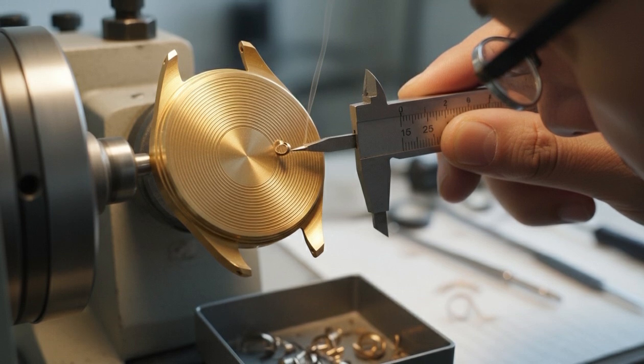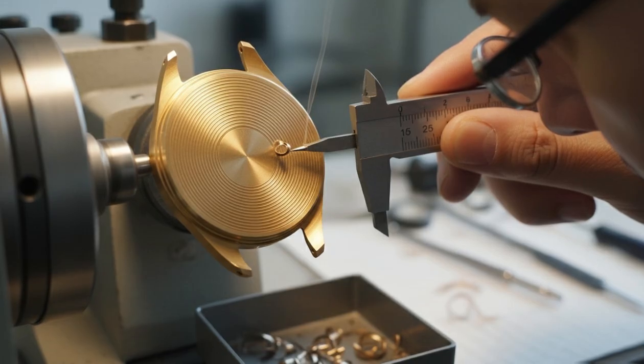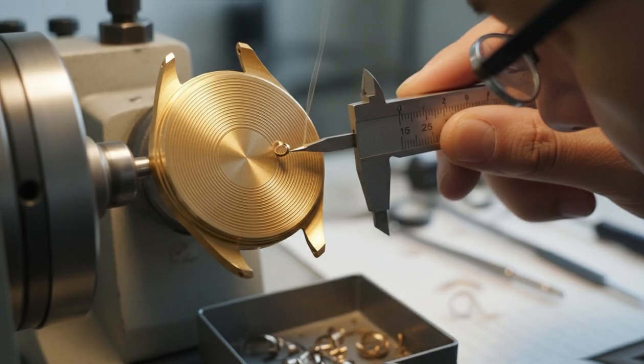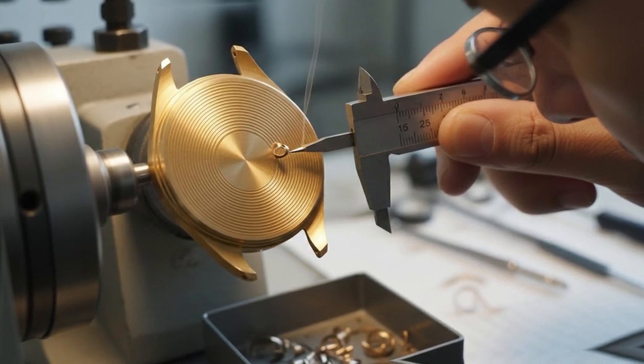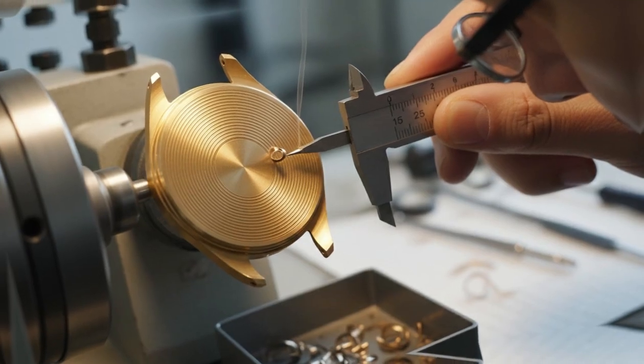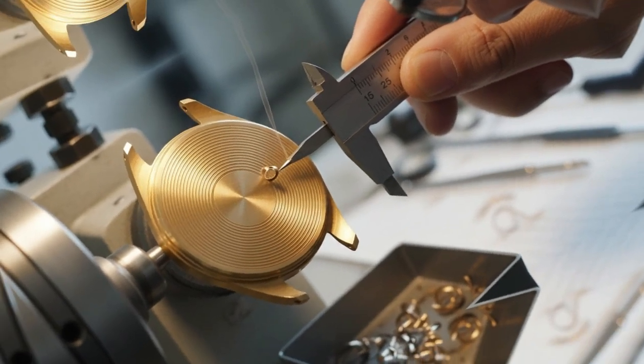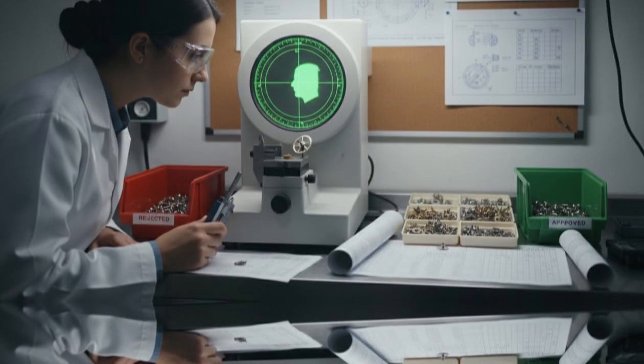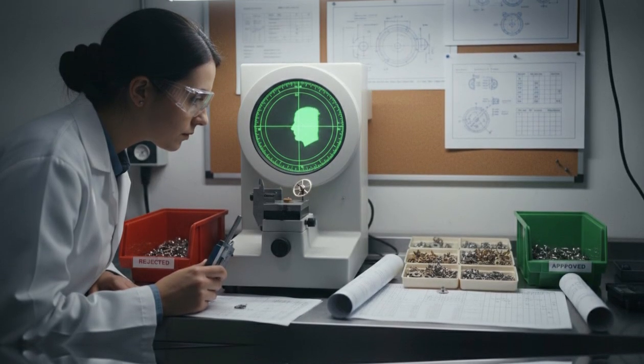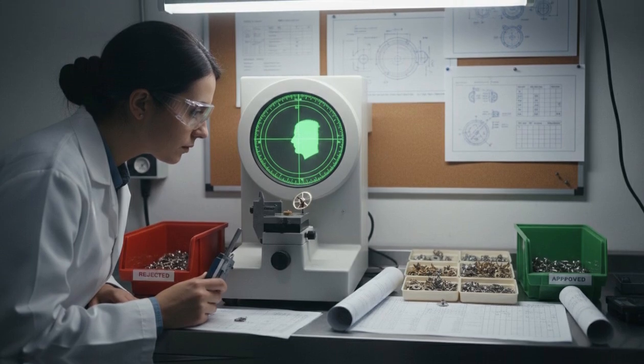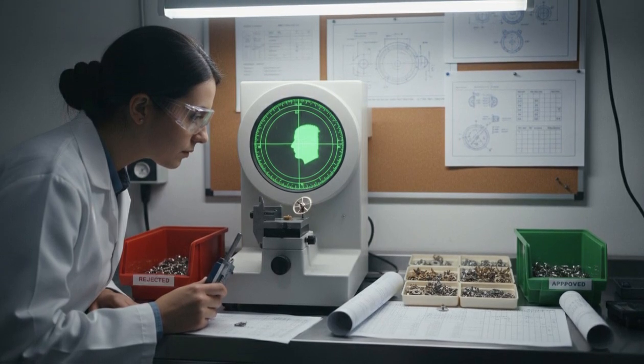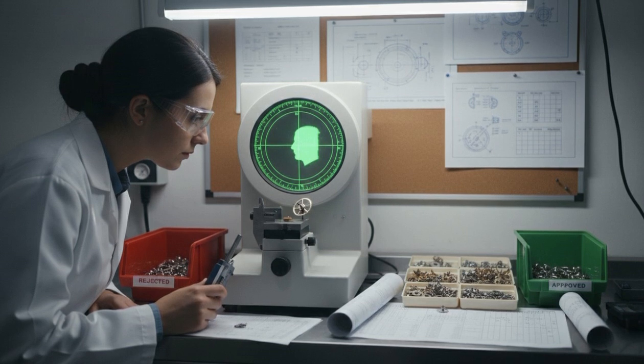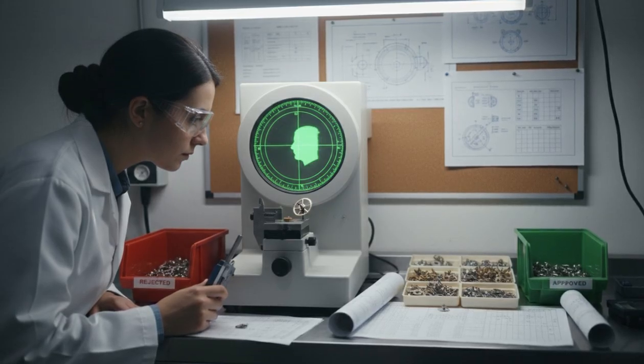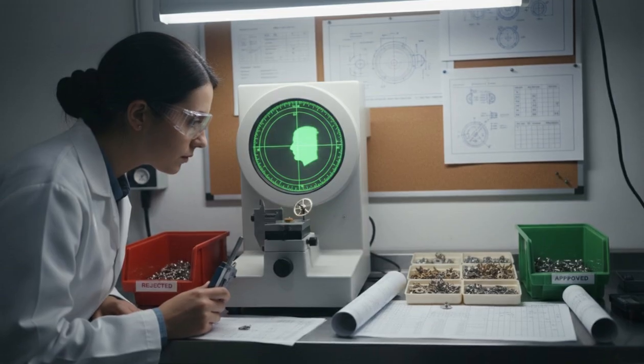The white gold alloy is even more complex. Traditional white gold achieves its silvery color by alloying pure gold with palladium and silver, but the result often has a slightly yellowish tint that requires rhodium plating to achieve a true white appearance. Rhodium plating wears off over time, eventually revealing the off-white base metal underneath. Rolex rejected this compromise entirely. Their white gold formula uses carefully calculated proportions of palladium, silver, and platinum to achieve a naturally white color that never requires plating. The alloy is inherently white, meaning a Rolex white gold watch will maintain its color for an entire lifespan without any maintenance.